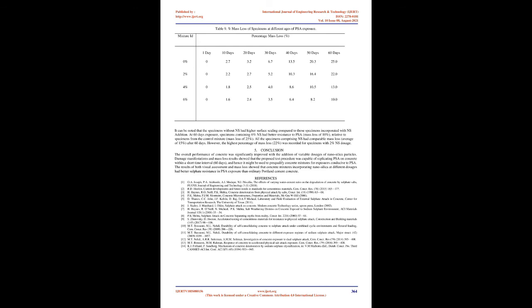Conclusion. The overall performance of concrete was significantly improved with the addition of variable dosages of nano-silica particles. Damage manifestations and mass loss results showed that the proposed test procedure was capable of replicating PSA on concrete within a short time interval, 60 days, and hence it might be used to pre-qualify concrete mixtures for exposures conducive to PSA. The results of both visual assessment and mass loss showed that concrete mixtures incorporating nano-silica at different dosages had better sulfate resistance in PSA exposure than ordinary Portland cement concrete.